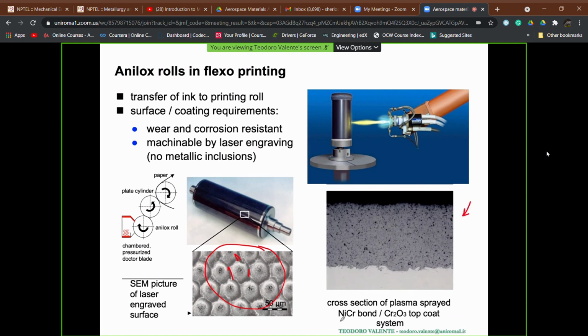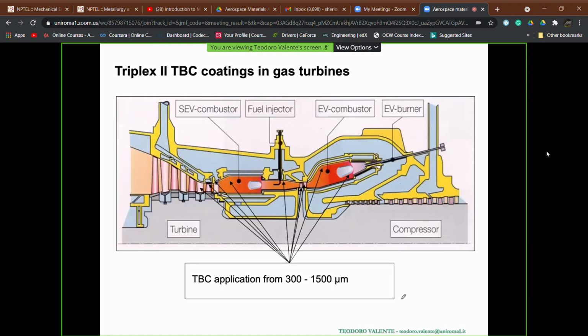In this case, it's a cermet coating in which we have a metallic phase, which is based on nickel and chromium, and a ceramic phase, which is not a non-oxide ceramic phase, like in the standard cermet materials, but is chromium oxide.